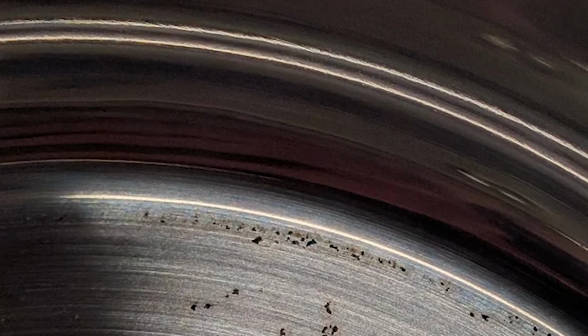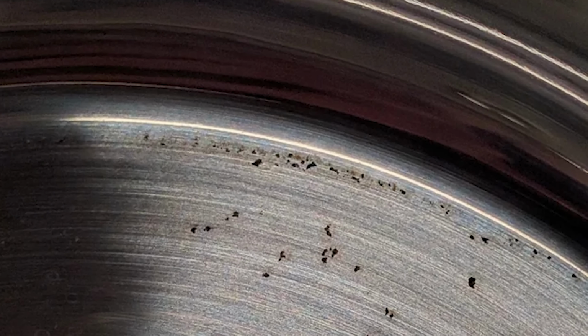In several compositions of the 200 series, the carbon content is higher than in 304, which increases the tendency for sensitization, that is, the formation of chromium carbide, and this paves the way for intergranular corrosion. In addition, sulfide inclusions associated with sulfur are preferential initiation points for pits.